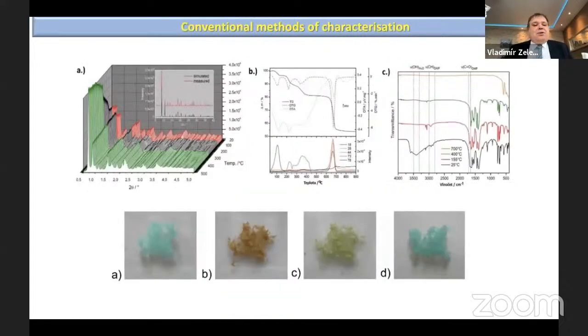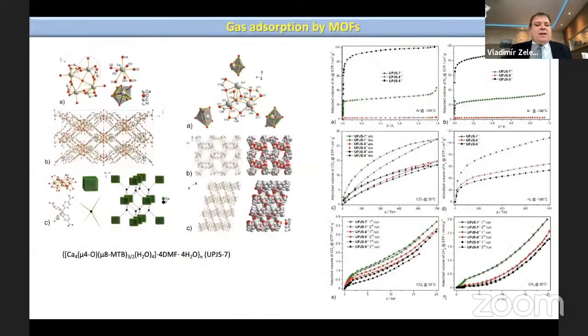This is just an example of the different methods we use for the study, because when you synthesize such a material, the pores are occupied by solvent molecules like water or dimethylformamide. So you have to remove the solvents from the porous structure. You have to remove them gently because otherwise the porous structure can collapse. But after removing, the sample is stable up to 400 degrees Celsius and can be used for gas adsorption and separation. And here is an example of the adsorption of different gases on one of the MOFs, the calcium version of one MOF: adsorption of nitrogen, argon, carbon dioxide, methane. Some of them are cryogenic, of course. Adsorption of carbon dioxide can be done in cryogenic conditions.